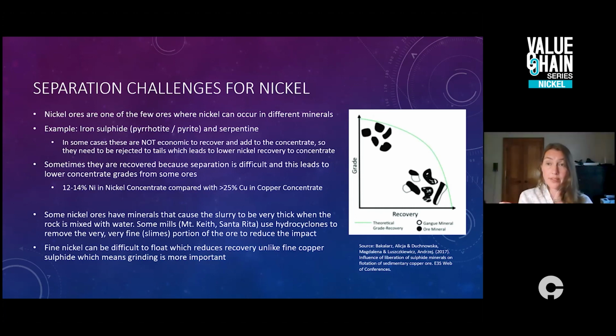And that could be from iron sulfides, or it could be in serpentine or olivine or magnetite. And so you have to start rejecting that. So there's definitely a point, and it's this grade recovery curve, where nickel concentrators balance that in terms of maximized recovery at a certain concentrate grade. But typically when you look at nickel concentrates, they will be generally lower concentrate grade than comparables in the copper industry. And that's really around the fact that the nickel can occur in multiple different minerals.